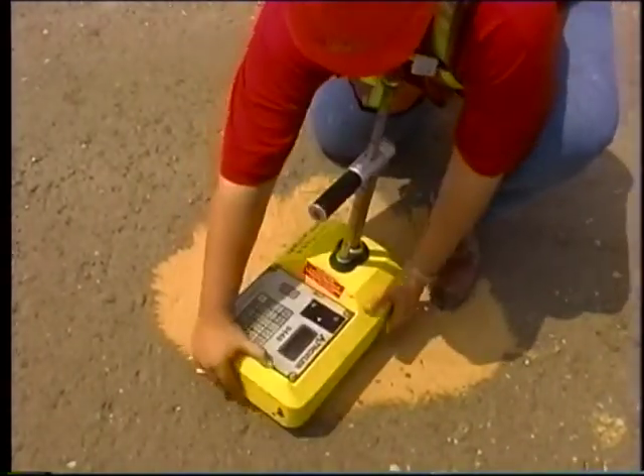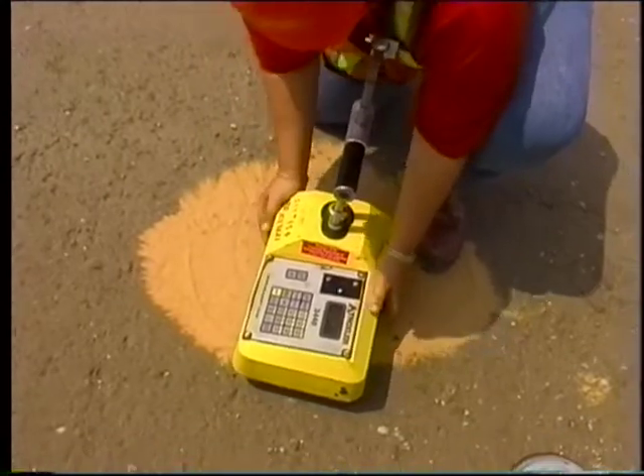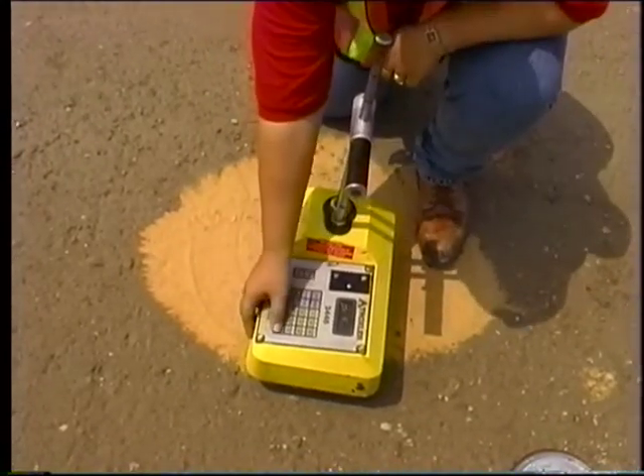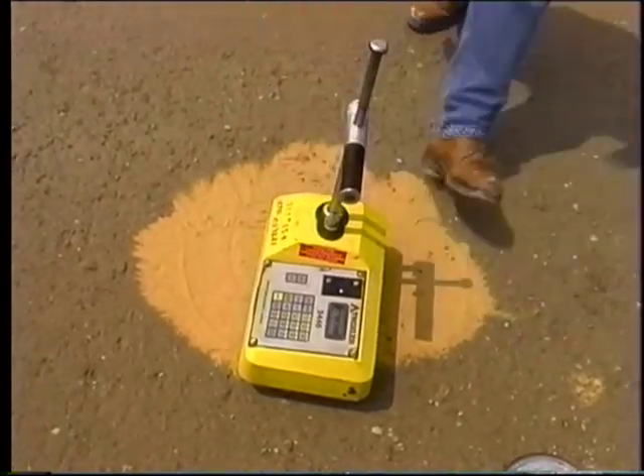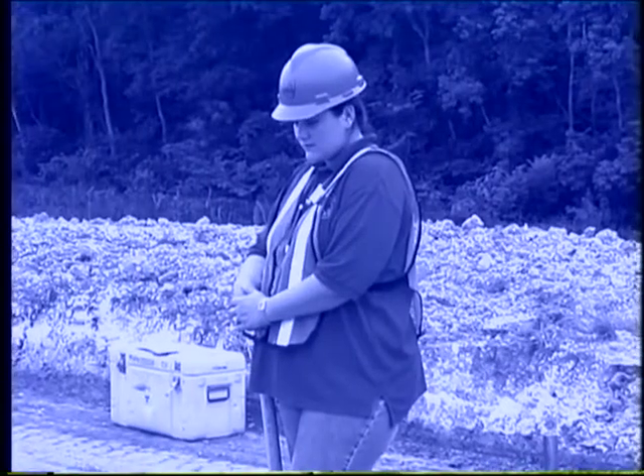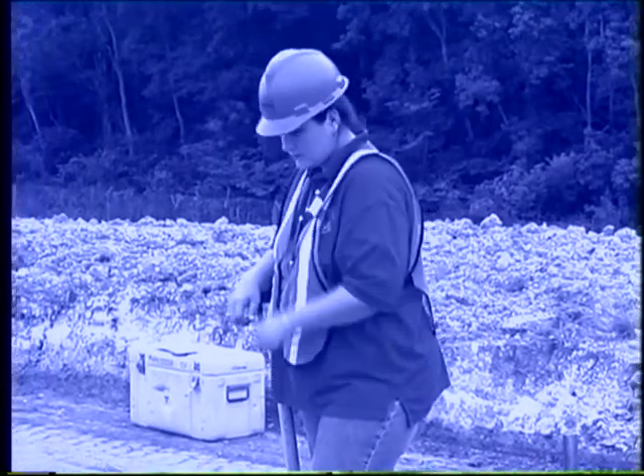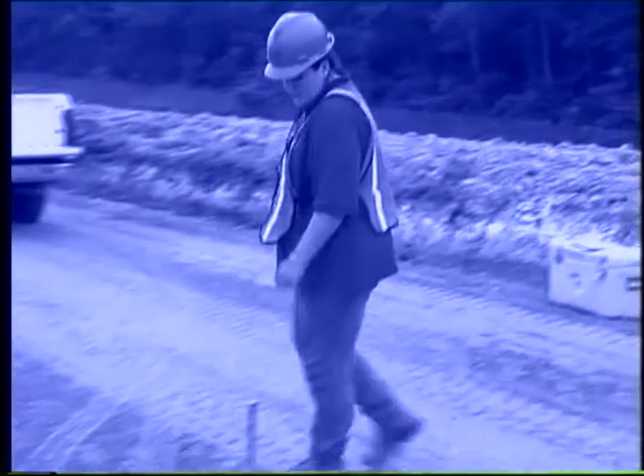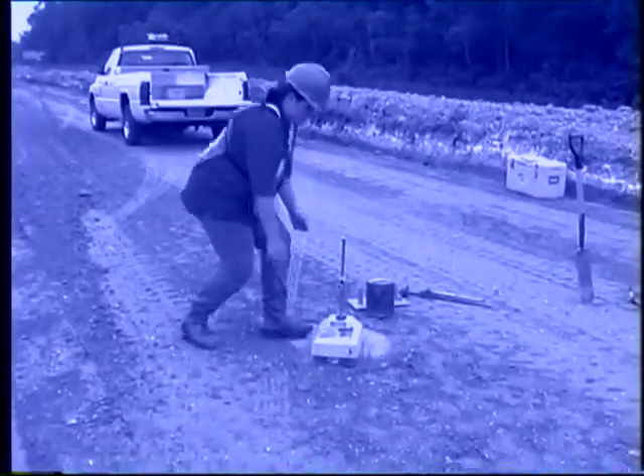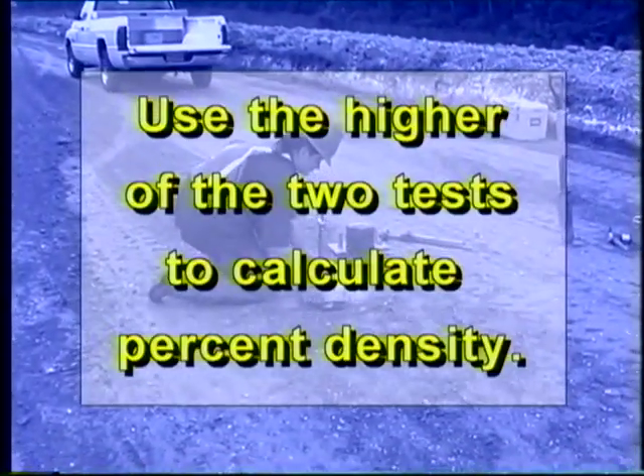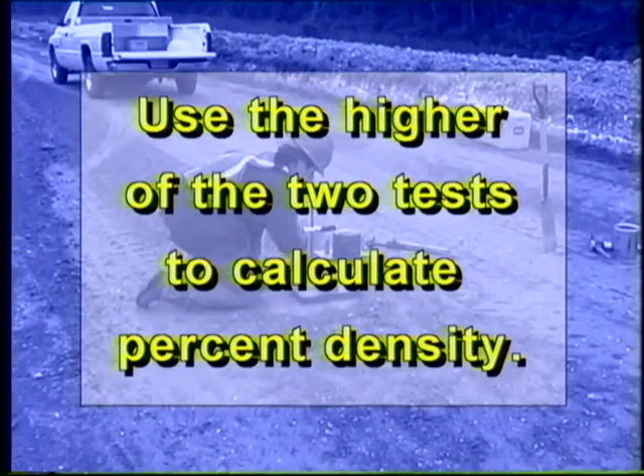If the dry density of any test is more than 48 kilograms per cubic meter, or 3 pounds per cubic foot below the highest dry density of the 3 tests, reseat the nuclear device in the same orientation as the original test and rerun the test to verify the results. Use the higher of the 2 test results, original and retest, to calculate percent density.